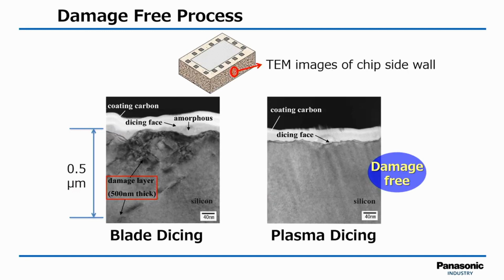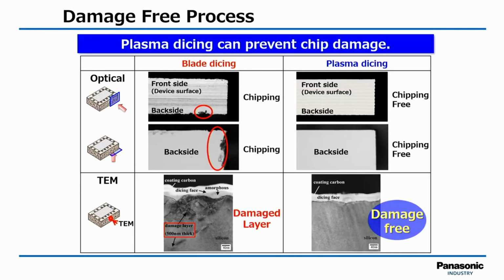You can see here evidence of the damage caused by blade dicing on the left, and on the right-hand side you see the plasma dicing result completely damage-free. Here's a closer look. If you look underneath or on the side of blade diced chips, you can see evidence of damage. And on the right-hand side you can see plasma diced chips, a totally damage-free result.